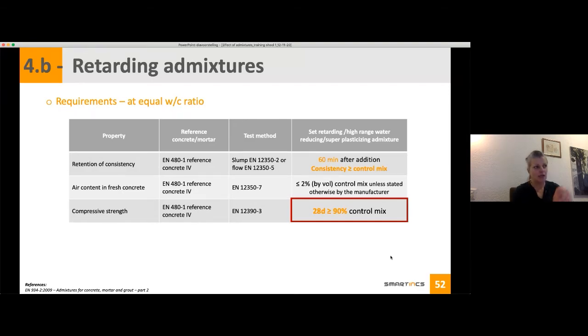And if you look at your compressive strength, it should be more than 90% of your control mix at 28 days. What I haven't mentioned, I think, is that for the super plasticizing admixture, when you fulfill the requirement at same consistency or same water to cement ratio, it's not mandatory to use the same dosage. So if you have the properties at equal water to cement ratio, it means that you can also have another dosage to have the other properties.